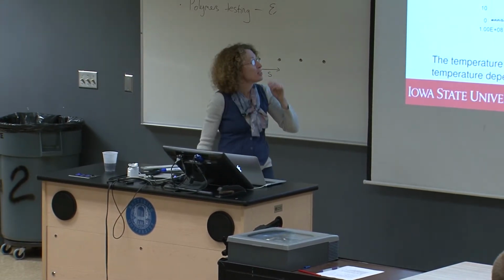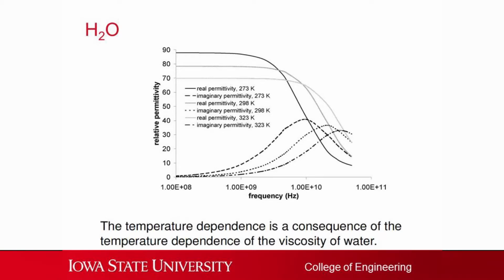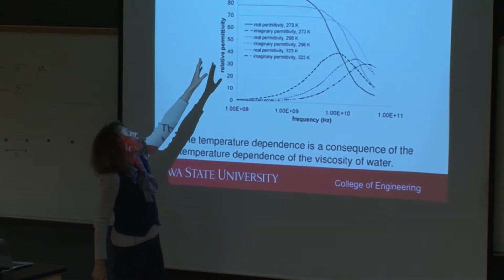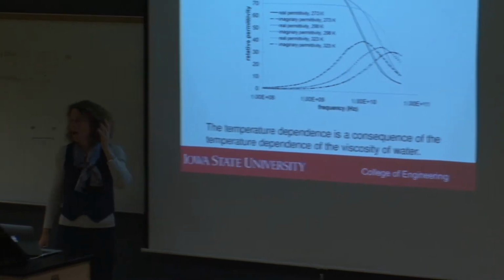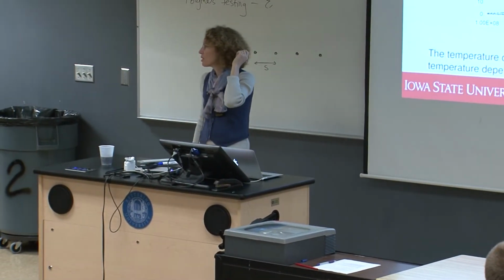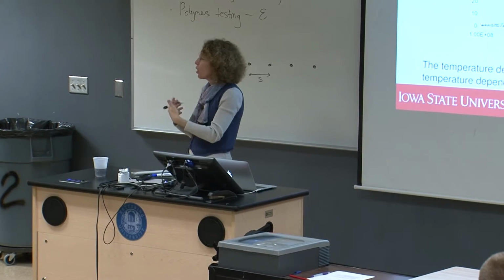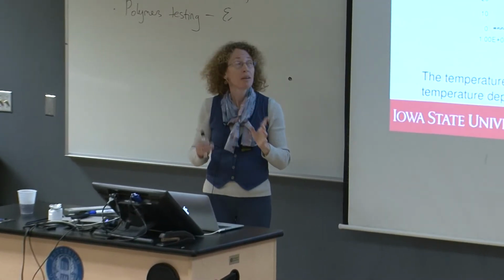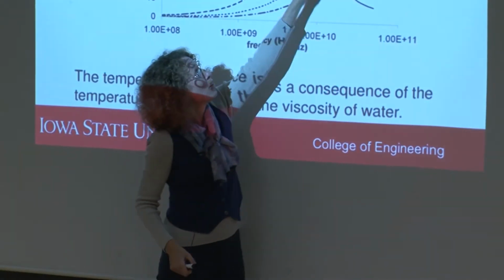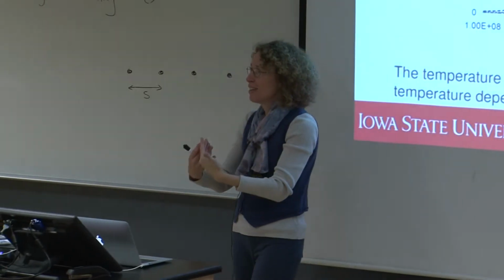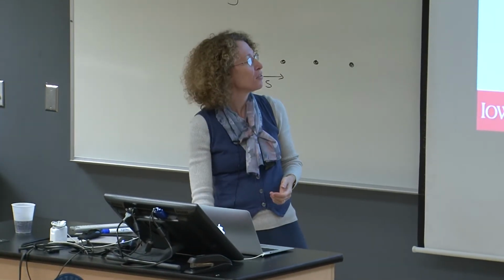So just to convince you, this is what permittivity looks like for H2O. The dark line is more or less 273 Kelvin, so there's a temperature dependence shown here as well. But as you see, the relative permittivity of water is pretty high. It's over 80 at that temperature. So water is a very polarizable fluid, actually, and this is why microwaves work. This is about the microwave frequency, and you can put a lot of energy as heat into water at about the frequency of microwaves.